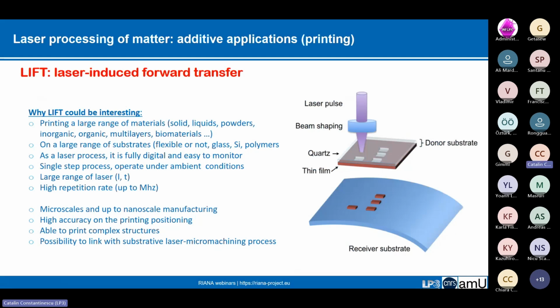Why LIFT? This technique, LIFT, which stands for laser-induced forward transfer, is now fully digital, which means we can fully control it with a computer. We can use designs that can be rendered by software, and it is a single-step printing technique compatible with virtually any material and substrate. The whole idea is to use a donor substrate which is transparent. The laser beam is focused at the interface between the donor substrate and the thin film. The thin film can be solid, like a simple thin film or a multi-layer structure, or it can be a suspension, like a gel, a paste or ink.